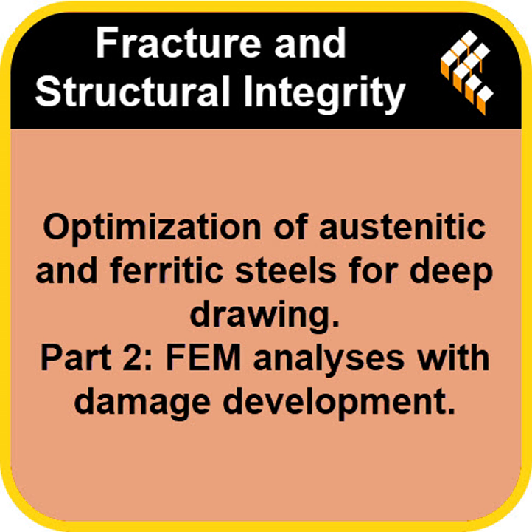And there's a number for that ability to spread the load after yielding. Yes, the work hardening coefficient, often called N. It measures how much the material strengthens as it deforms plastically. A higher N means as one area starts to thin, it gets stronger, forcing the deformation to move to adjacent, weaker areas. So it prevents the deformation getting too localized. Precisely. It distributes the strain. And the study found 304 had a much higher average value, 0.329 compared to just 0.177 for 430. Wow, that's a huge difference, almost double. It makes a massive difference in resisting that localized necking that leads to fracture.